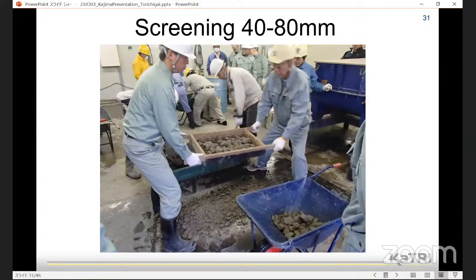The photo shows a situation where coarse aggregate of 40 millimeters or more is being screened. It's very hard work. At the construction site of the concrete dam, this work is done once every 1 to 2 hours for the quality control test of the dam concrete.